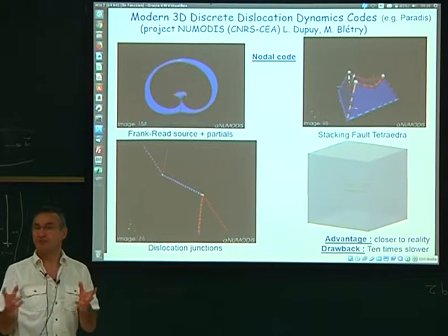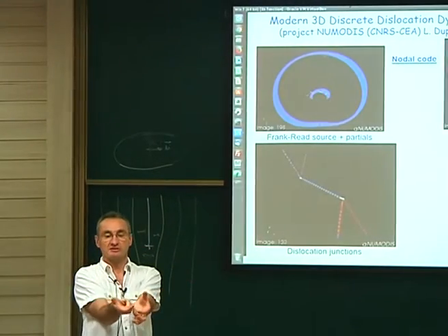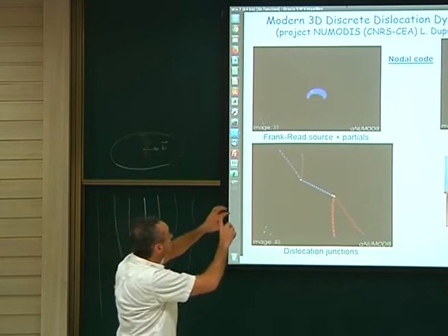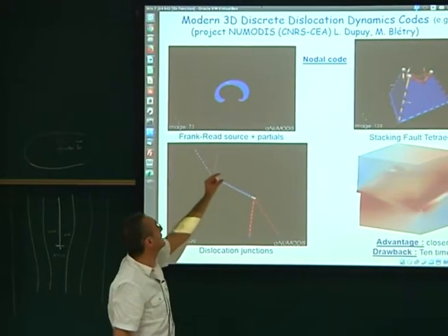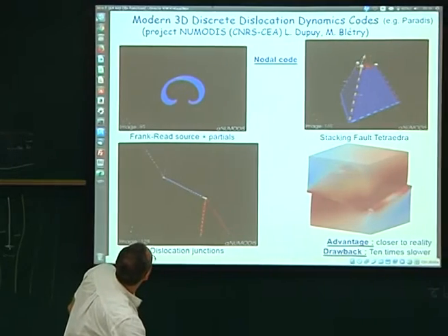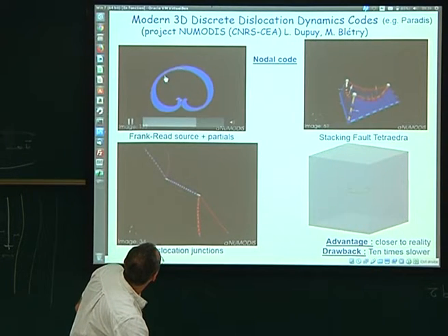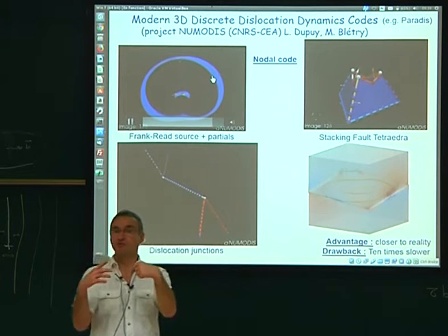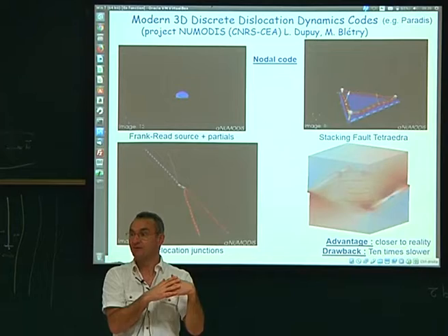So this is different from what you can see in textbooks. You don't have a continuous, same-size dissociation length everywhere. You have some regions where the dissociation length is short. This is typically what happens here. It is very short at this place, and very big at that place, just because each of the lines wants to get aligned with its own Burgers vector. You see what I mean?